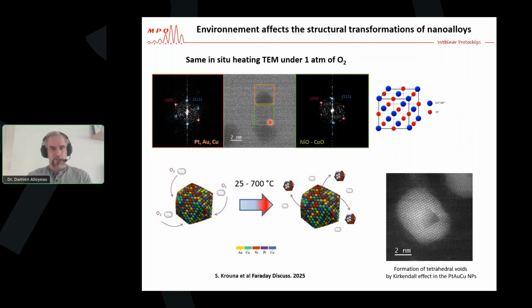And this time you have the formation of these nickel cobalt oxide platelets in between the nanoparticles, or at the surfaces of the nanoparticles. And due to the Kirkendall effect, the remaining platinum, gold, and copper nanoparticles present some voids, due to the fact that the diffusion of the nickel and the cobalt toward the surface is faster than the insertion of oxygen within the structure. So you leave a void inside the nanostructure. So keep in mind, of course, that the structural transformation of your materials during the synthesis is affected by the environment.